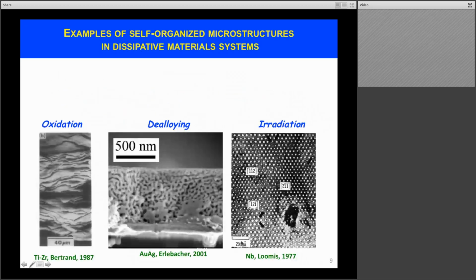I start here with a couple of examples on the next slide to illustrate that self-organization is observed in many non-equilibrium material systems, from oxidation, where you see the formation of these layers of oxide here, to de-alloying, where using electrochemical means we can remove a less noble element from a matrix, leaving behind here a porous plug, which might be interesting for catalytic applications or filtering different molecules and particles.